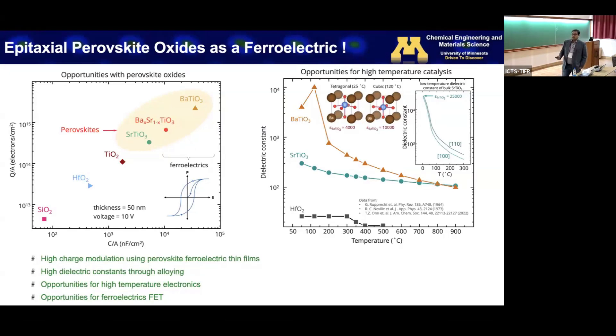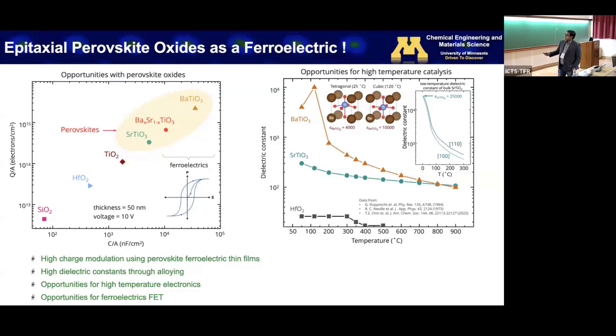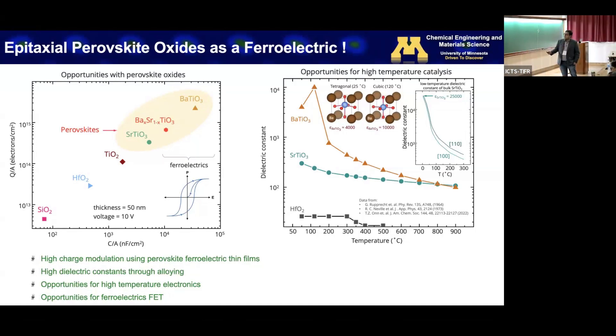Some of these materials are also ferroelectric, so you can have a spontaneous reversible and switchable polarization. Some of these materials which are great at room temperature — if you think about high-temperature electronic applications — are also quite interesting. You can see the dielectric constant as a function of temperature for some prototype complex oxides; the dielectric constant remains in the hundreds even at temperatures exceeding 500 degrees Celsius. Whereas conventional dielectric materials like hafnium oxide start to go really bad for high-temperature applications. So these can be promising materials for high-temperature electronics.